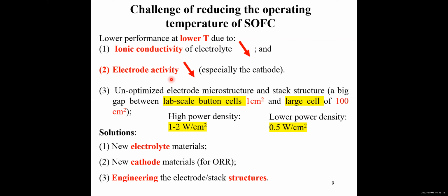And from the engineering design point of view, the fuel cell performance is also not optimal because there is a big gap between the lab-scale button cell performance and the large cell performance. For example, for button cells we can achieve very high power density, probably between 1 to even 2 watts per centimeter squared. But for large commercial scale cells, the power density is normally around 0.5 watts per centimeter squared. This is mainly due to the unoptimized engineering design.